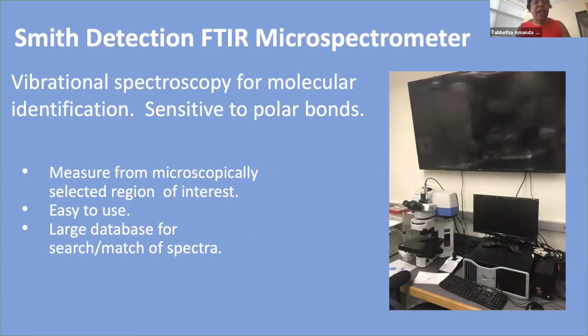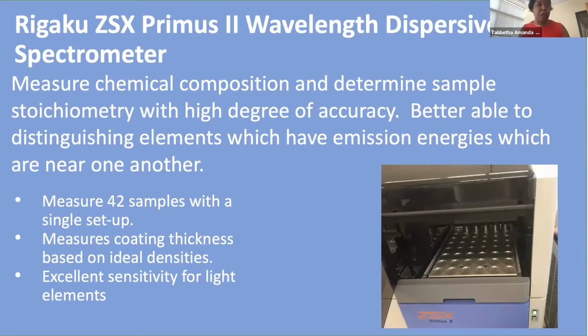Along with that, and actually in the same room as it, we have an FTIR spectrometer. And again, this is very sensitive to polar bonds. It's unable to do confocal imaging, but we can actually do spectral microscopy. So we're able to image the surface of your sample and collect the spectroscopy signal from the region of interest. And again, for both of these instruments, we have search match database capabilities.